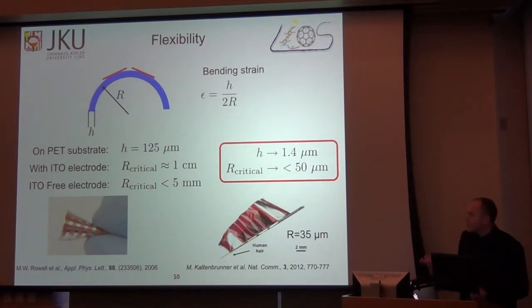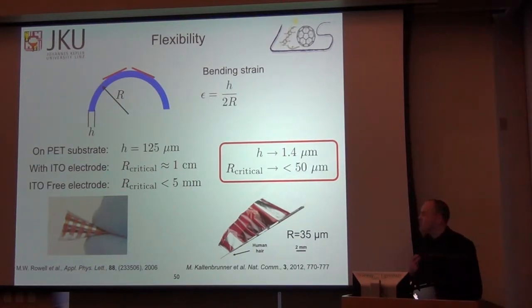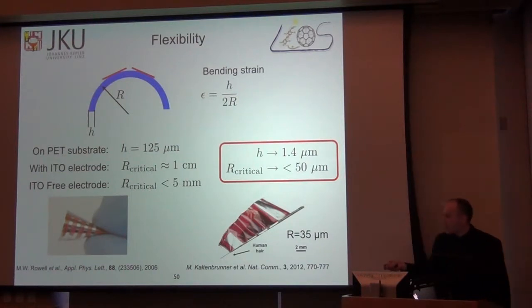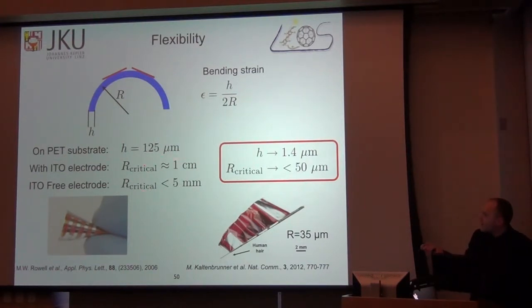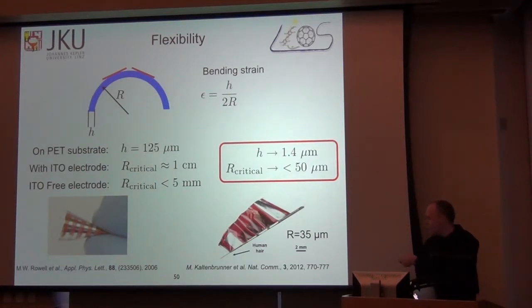For organic photovoltaics, and this is based on results from 2006 from my institute, Linz Institute for Organic Solar Cells, in combination with Michael McGehee's group at Stanford. If you have a 125 micron thick substrate with ITO-free electrode like we have, their critical radius was somewhere less than 5 millimeters. So by shrinking the thickness by roughly a factor of 100, we estimate that the critical radius would be about 50 microns or less, which we tried to demonstrate originally by wrapping the solar cell around a human hair with a radius of 35 microns. That's very difficult to do.